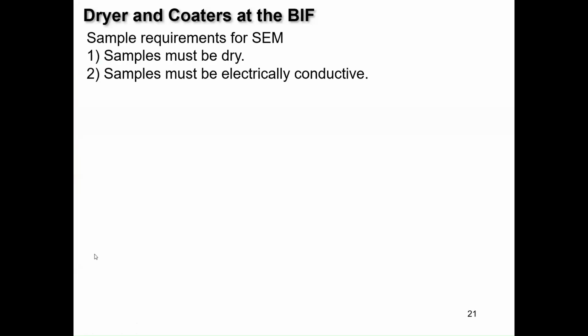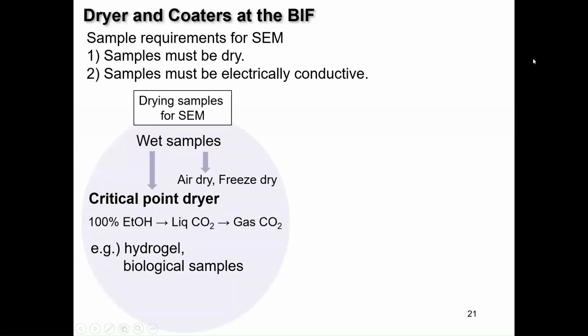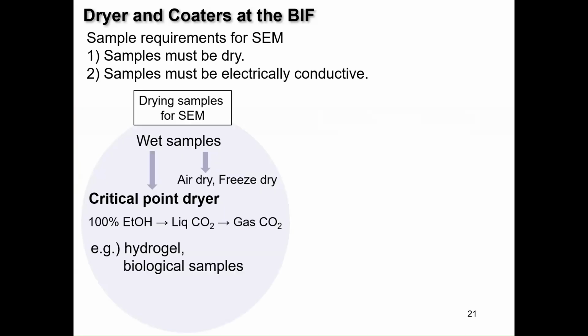So I want to switch to the dryer and coater. Sample requirements for SEM: because the SEM column is under high vacuum, samples must be dry. If there's any liquid, it gets vaporized and contaminates the electron column. And also samples must be electrically conductive. So if your samples are wet, researchers do air dry, oven dry, or freeze dry.